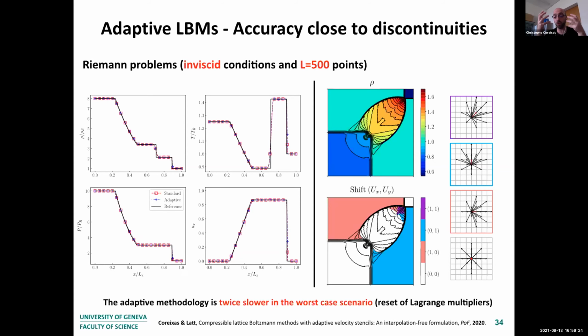And to do that, you don't know the values of the Lagrange multipliers. So what we do here is reset these values, meaning that we reset the root-finding solvers, which means that we locally increase the number of iterations to converge toward the equilibrium that we are looking for. Even by doing that very naive approach, we only divide the performance of the code by a factor of 2, meaning that by using something smarter, we would only lose like 30 or 40% of efficiency.